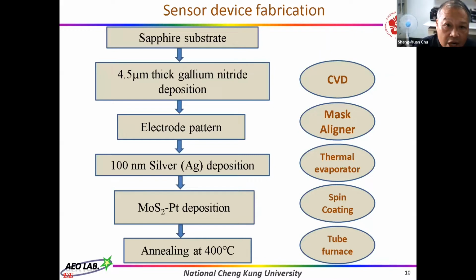The sensor device is fabricated using this flowchart. We use the sapphire substrate. After cleaning, 4.5 micrometer gallium nitride is deposited by using the CVD method. And then we use the mask aligner to do the electrode pattern. Then 100 nanometer silver was deposited by using the thermal evaporator. Then we use a spin coater to make the MoS2-Pt films. Then the films were annealed at 400 degrees, and finally we get the devices.